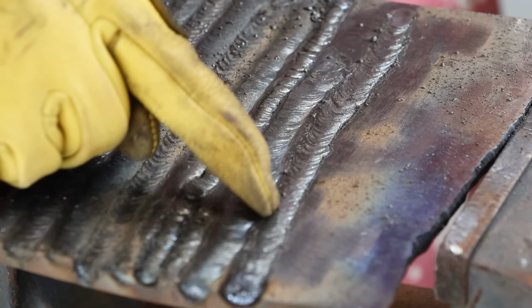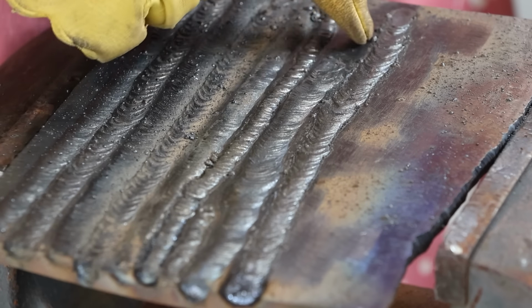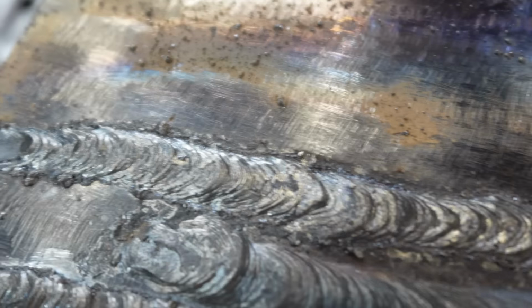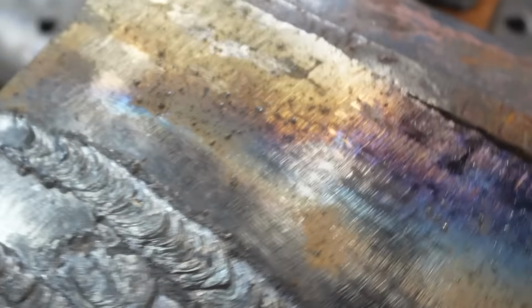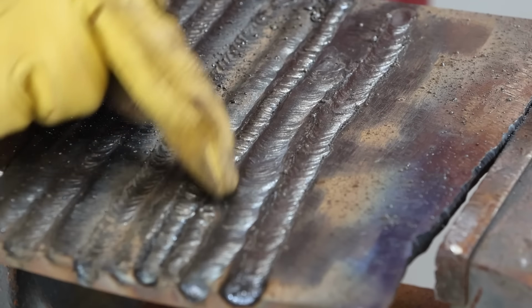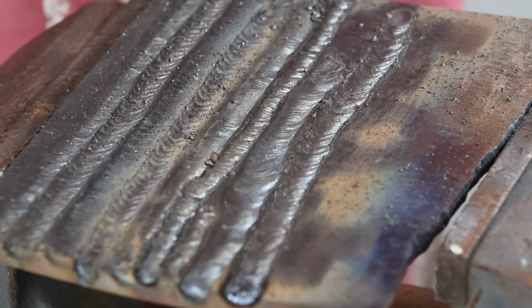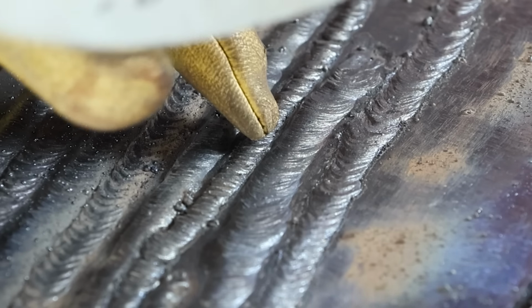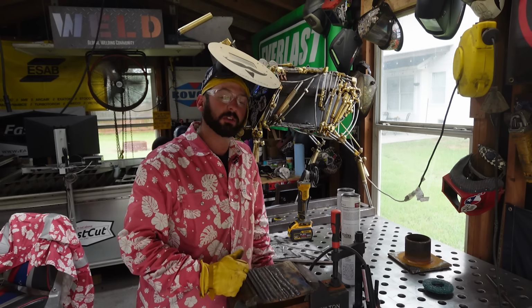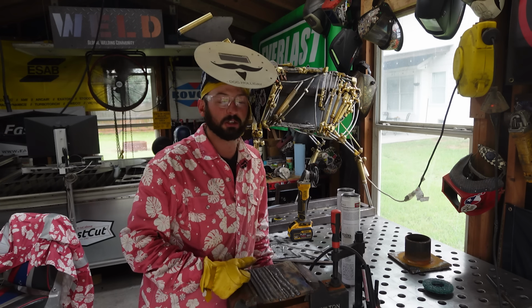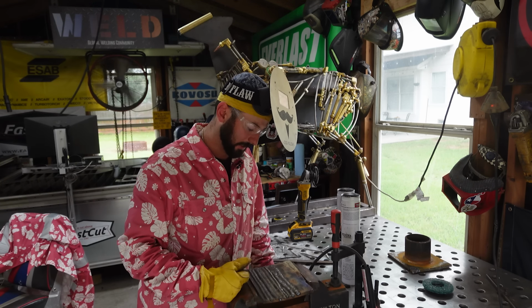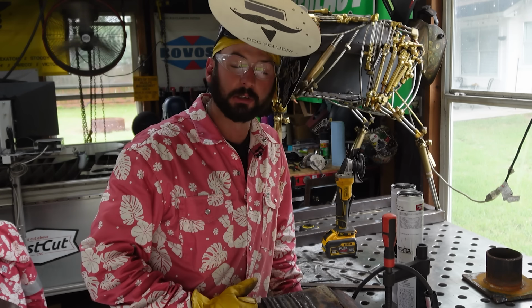You see you got a little bit of a skinnier bead, and as we get wider, we get a little bit more undercut into the weld right back here on the 6010 version. Things get wider, more of a spray kind of situation. The 7018, similar effects. We've got a much wider bead. There's a couple really small pinholes. But typically if you're seeing porosity with a 7018 and you're long arcing it, that's what's happening right there. Being in the flat position is probably the most forgiving.